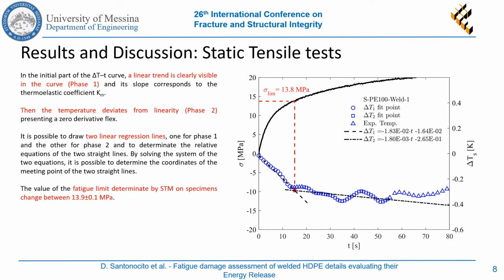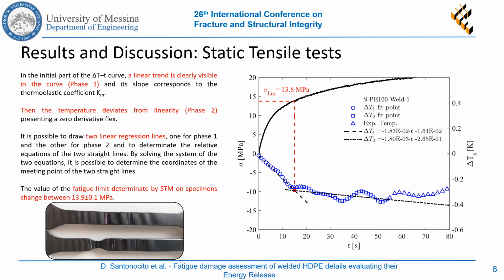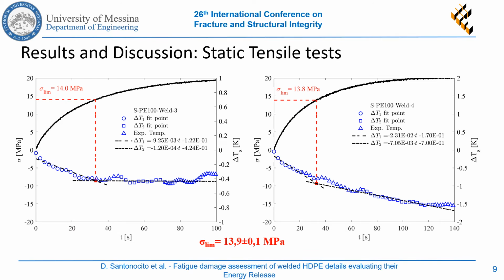The corresponding value of the applied stress could be related to the microscopic stress that introduces the first microplasticization phenomena in the material. All the tested specimens failed in a section far away from the welded area. The other two static tensile tests exhibit the same temperature behavior. The value of the limit stress assessed by the static thermographic method is equal to 13.9 plus or minus 0.1 megapascal.